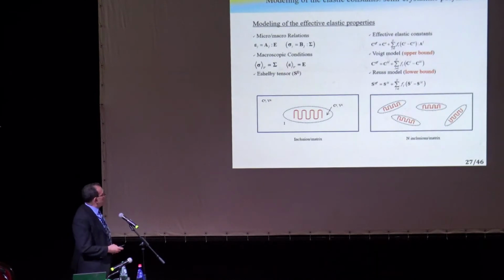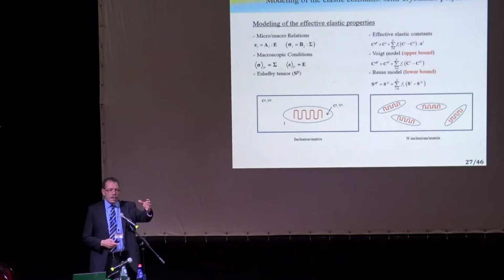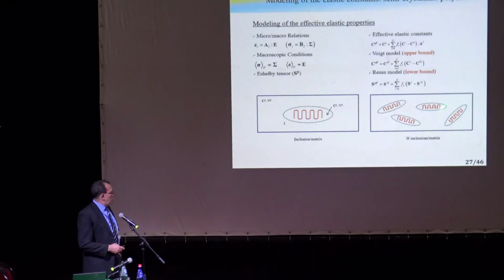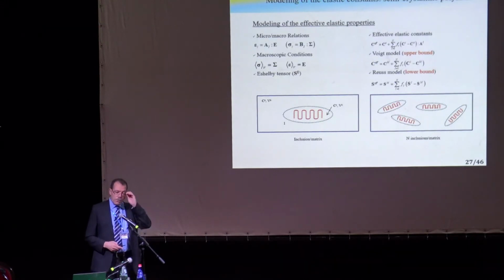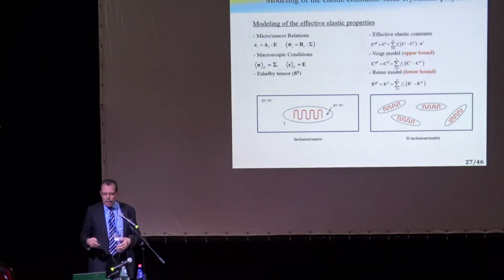Now, if we start with just the elastic properties of semi-crystalline polymers, you have a crystalline phase and an amorphous phase, and it depends on the crystallinity. For polyethylene, for example, if it's low density polyethylene, you have 30–40% crystallinity. If you go to high density polyethylene, you can go to 70–75% crystallinity and so on.